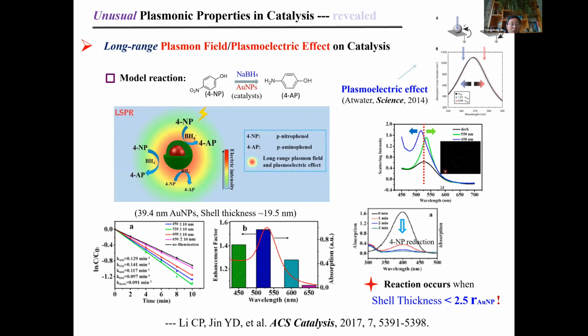In the model reaction of 4-nitrophenol to aminophenol, by using gold-silica core-shell nanoparticles as catalysts, we revealed a long-range plasmon field and plasmon-electric effect on catalysis. The plasmon-electric effect was first found by Professor Atwater at Caltech in 2014.